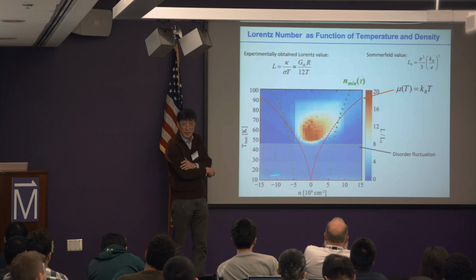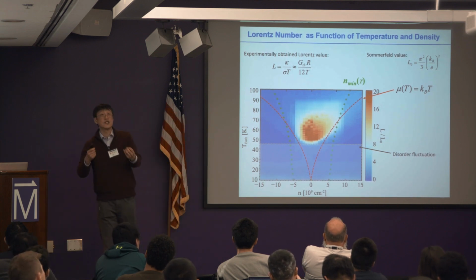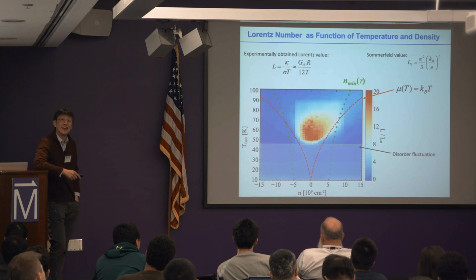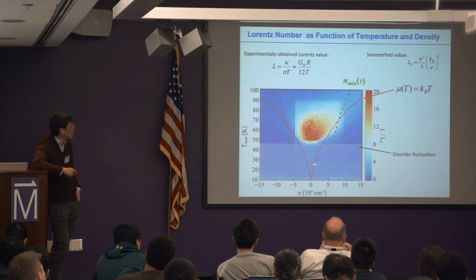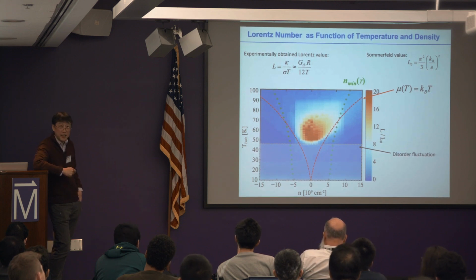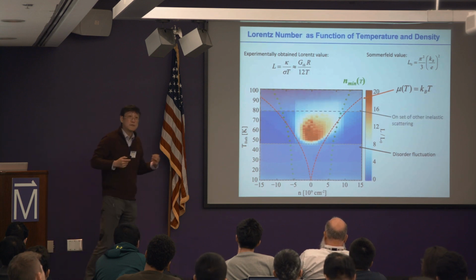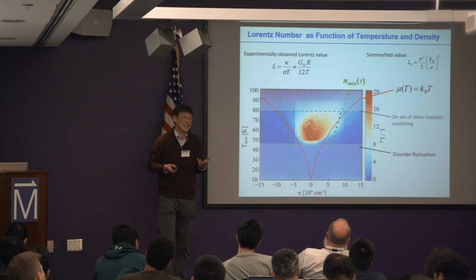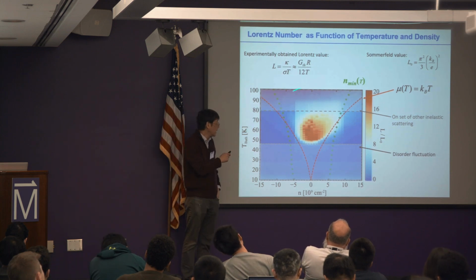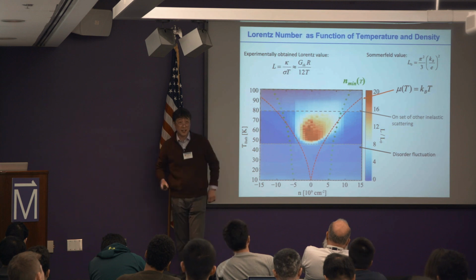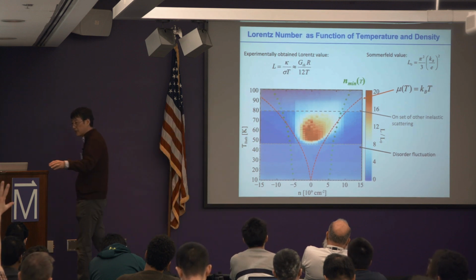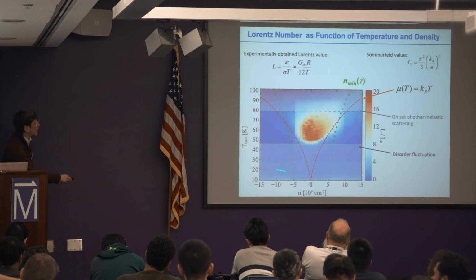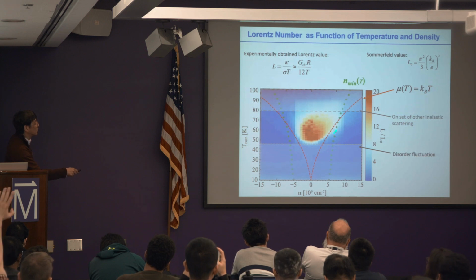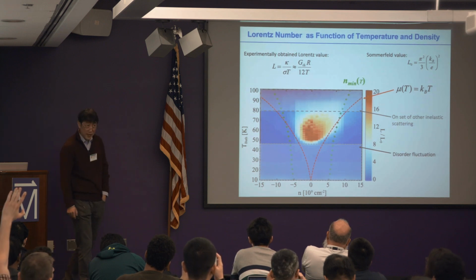Basically, this is a disorder-dominated region where we restore the degenerate system, such that the Wiedemann-Franz law holds. And above this temperature, at higher temperature, electron-phonon scattering cannot be ignored anymore, and especially electron-phonon inelastic scattering, which is the more important part, will dominate and break down the simplistic description we had in the beginning, the hydrodynamic description. So more or less, we explain why we expect to see these violations of the Wiedemann-Franz law nicely cornered within the region that we expect. Okay, so that's it.